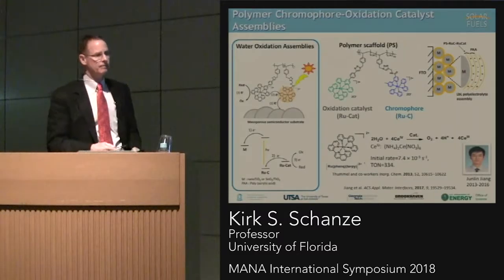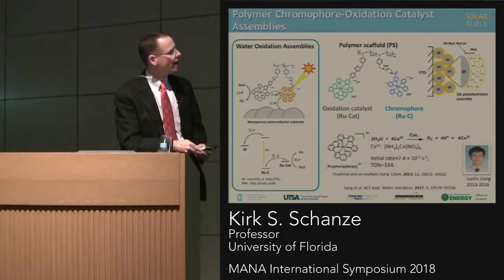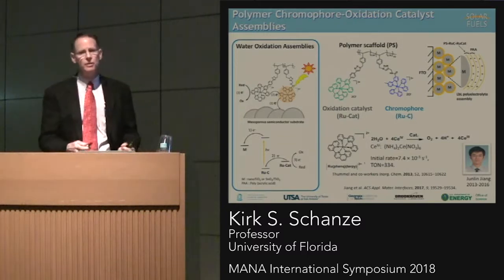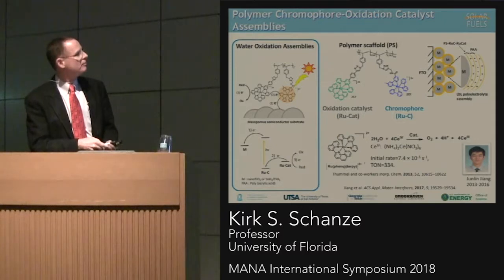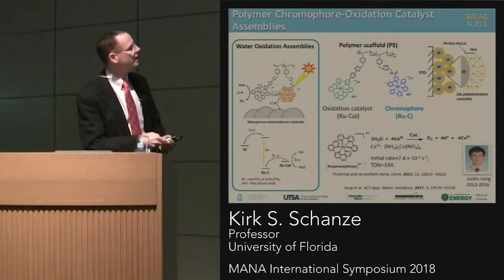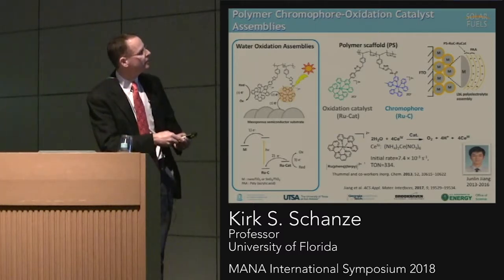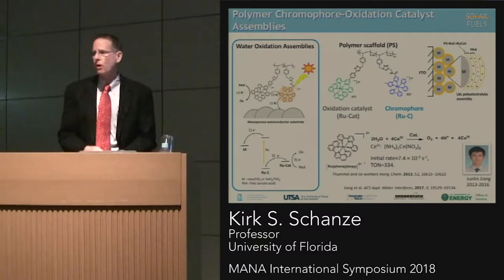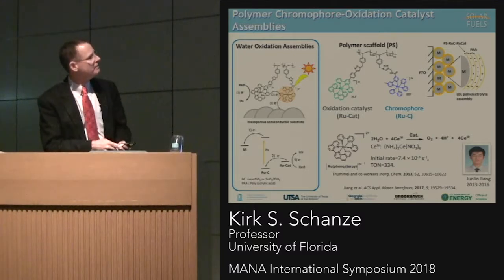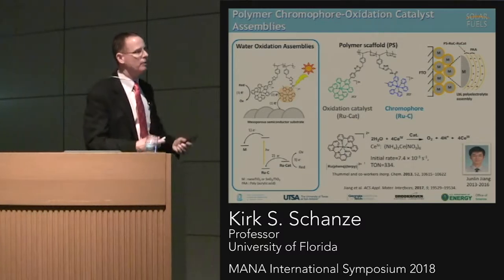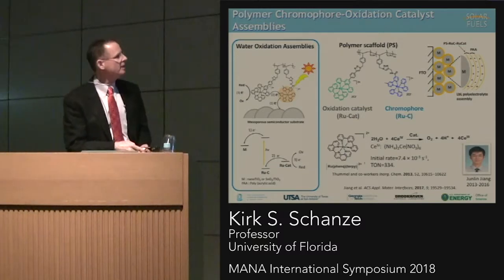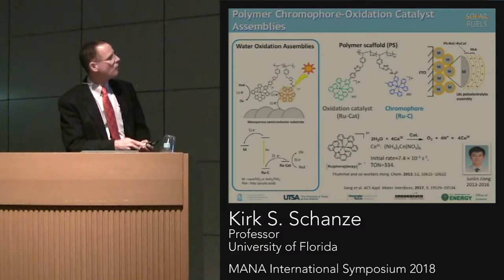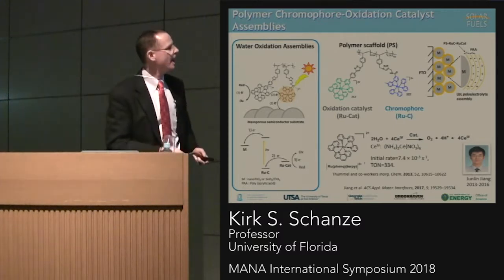To go beyond that, what Junlin Jiang did in his graduate work was to develop what we truly call polymer chromophore-catalyst assemblies. Here again, we use the same polymer backbone. This is polystyrene. But what Junlin did was attach both light-absorbing chromophores as well as catalyst centers. So this ruthenium that I'm circling is what we call a single site water oxidation catalyst. And we can vary the ratios of these systems, allowing us to control the stoichiometry. Again, this catalyst is not the best for water oxidation, but it is a competent catalyst.